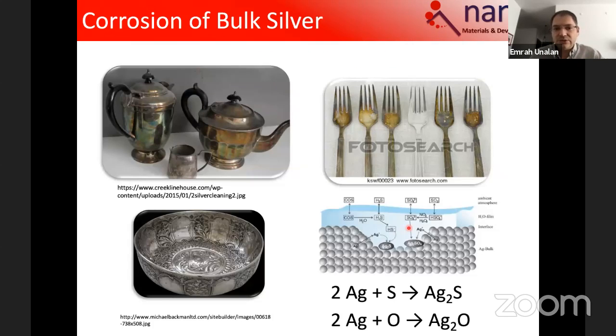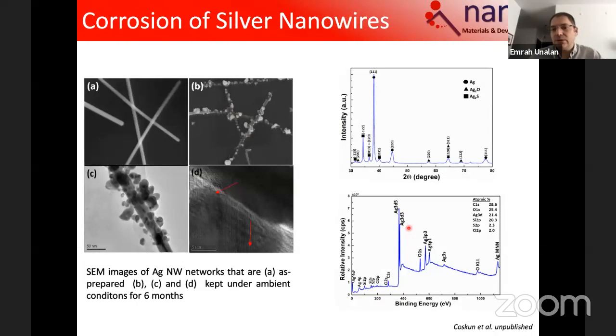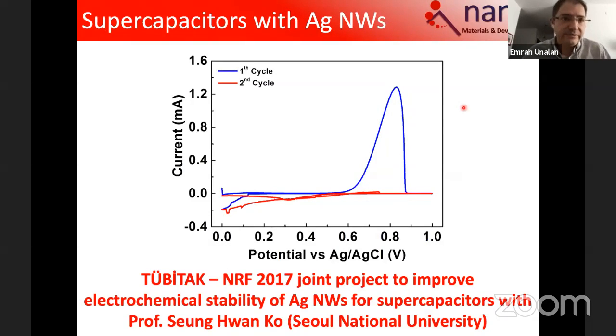And in fact, this stability issue is not just for nanowires, not just for nano-sized materials, but also for bulk materials. This is called tarnishing and has been known for years. In that case, it's a competition between sulfurization and oxidation, so-called tarnishing. For sure, this necessitates tens of microns of material, and unfortunately, in the nanowire network, we don't have this much thick material. So we have to be very, very careful in protecting the nanowires against sulfurization and oxidation. The sulfurization also acts on nanowire networks. So it's again a competition between oxidation and sulfurization, which eventually completely kills the network, and you cannot read any resistance or conductivity, if you wish, from these thin films. So that is the environmental stability.